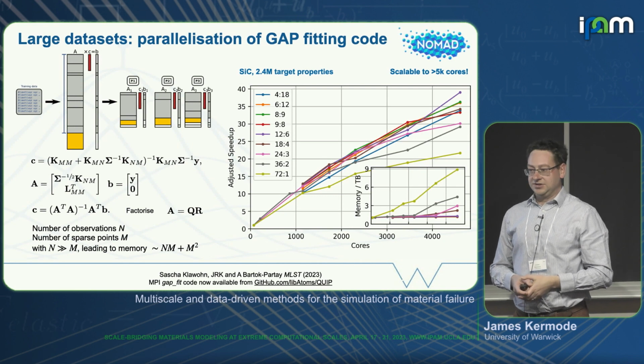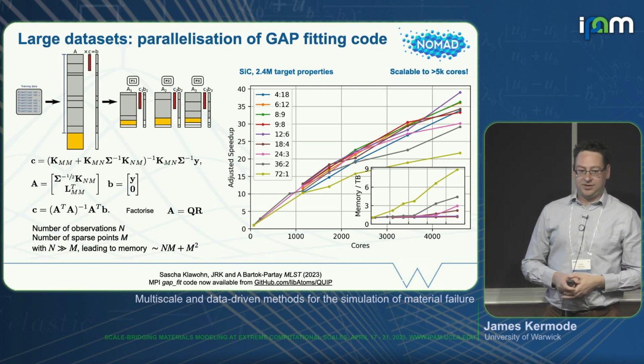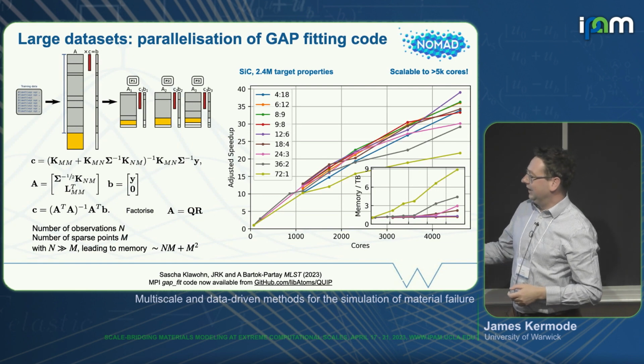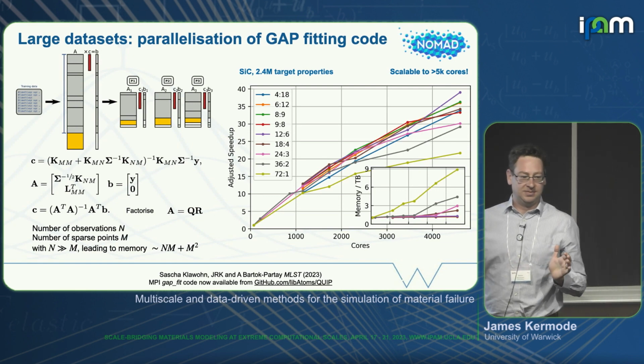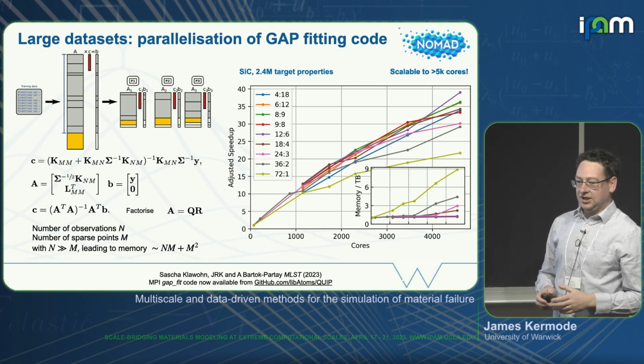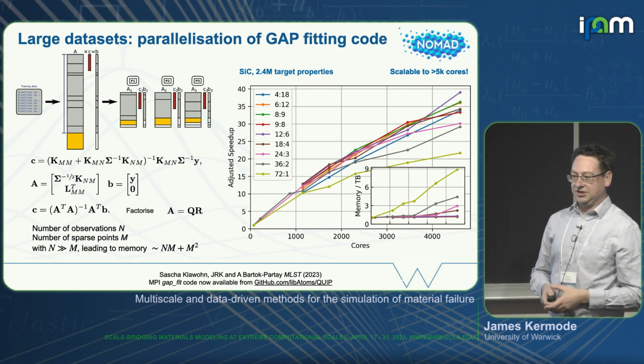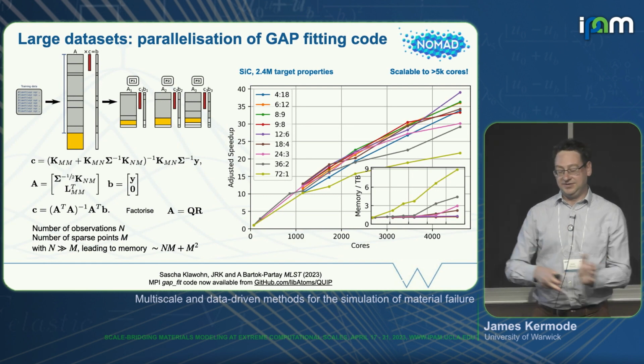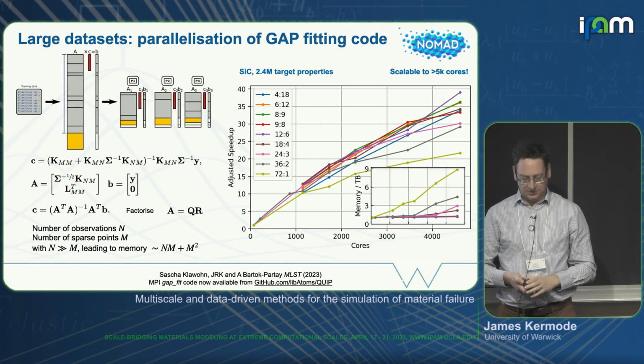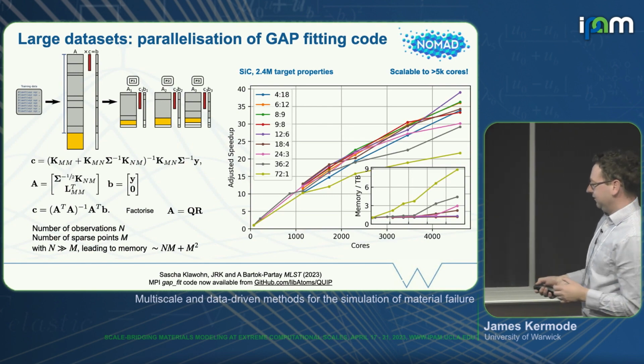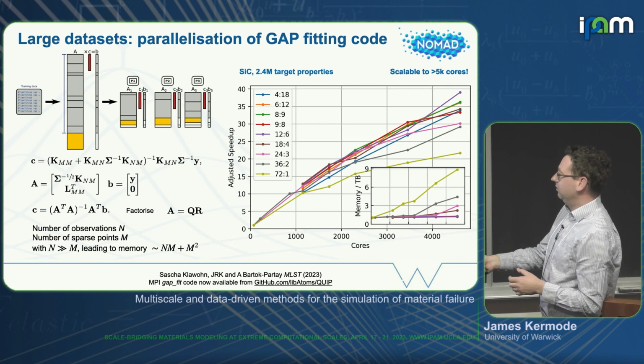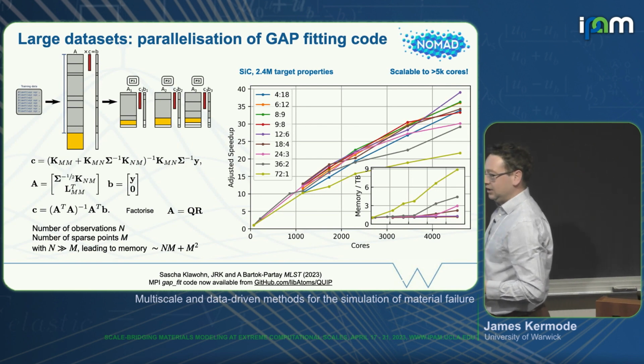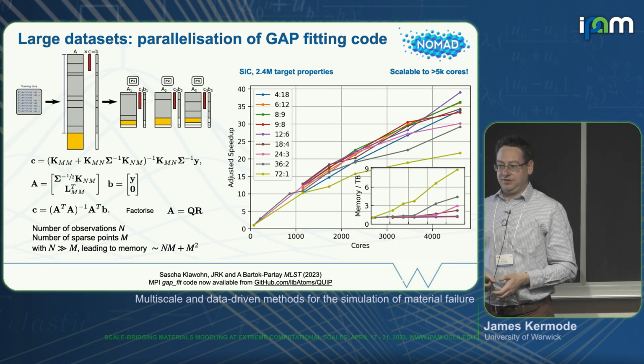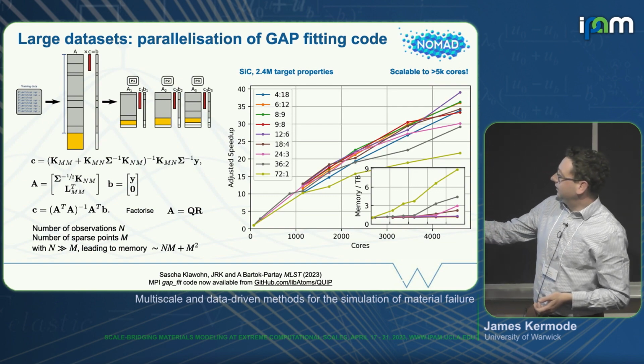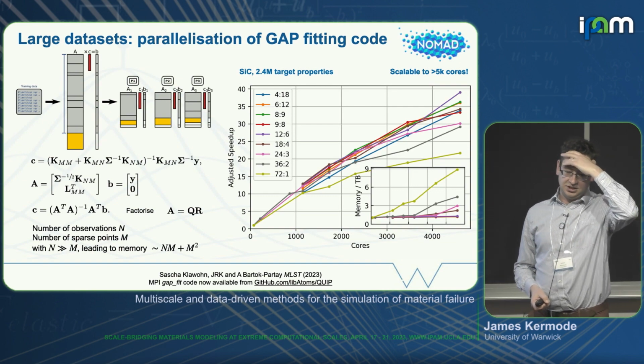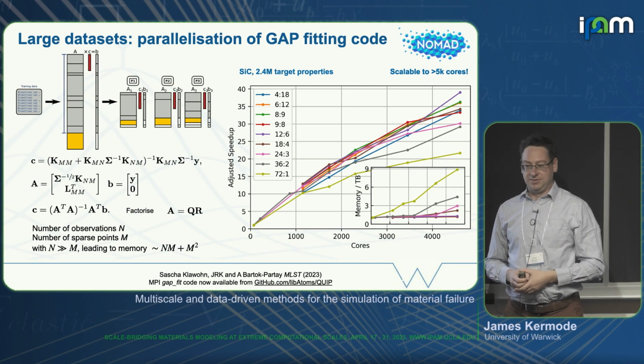That helps you in two ways. First of all, you can parallelize trivially over the evaluation of the descriptors. So filling in this matrix is much faster because you can do it in parallel. And it also helps you because you don't need to store it all in one place. So you can use your entire HPC facility's memory. You don't need all the memory on one node. The scaling is pretty good. So we get to 5,000 cores or so with quite a good speed up factor, 40 or 50. And that takes the time to train one of these models with millions of configurations, like the silicon carbide example I just showed you, down from a few days to maybe a few minutes.